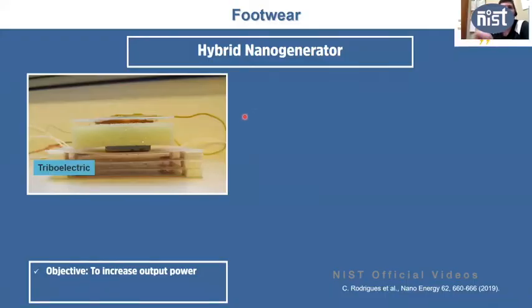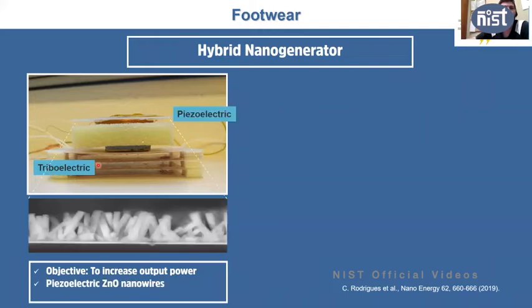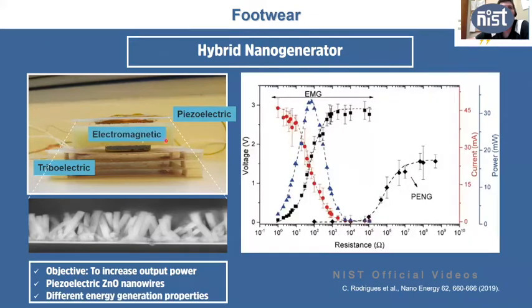To increase the power that we are obtaining, we made a hybrid nanogenerator where we have the triboelectric at the bottom. Then we put zinc oxide nanowires to make a piezoelectric nanogenerator on top. And we also added an electromagnetic generator with a coil and a magnet on these 3 structures. This is what you have. The electromagnetic generates the highest power here, at the lowest resistance. The triboelectric is at a higher resistance, and the piezoelectric is the one that gives you the smallest power and the smallest output voltage.